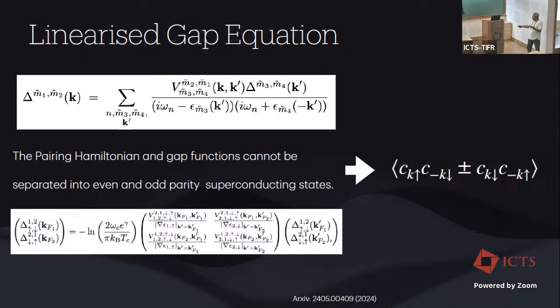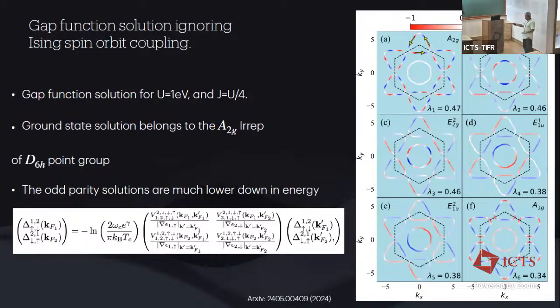The gap equation is kind of, as you can expect from this full formalism, a little more complicated with off-diagonal and diagonal contributions that come into the picture. And if you were to consider, let's say, the scenario where you first ignore spin-orbit coupling in your system, then I show you what are the solutions that come out by diagonalizing this gap function, which is equivalent to diagonalizing this matrix that you see out here. So there would be a lot of solutions that come in where the ground state energy is given by the largest eigenvalue in the problem.